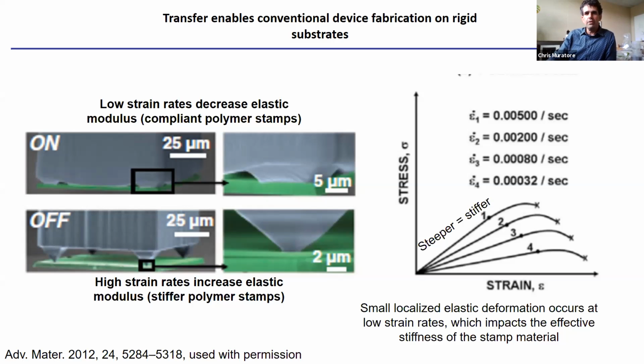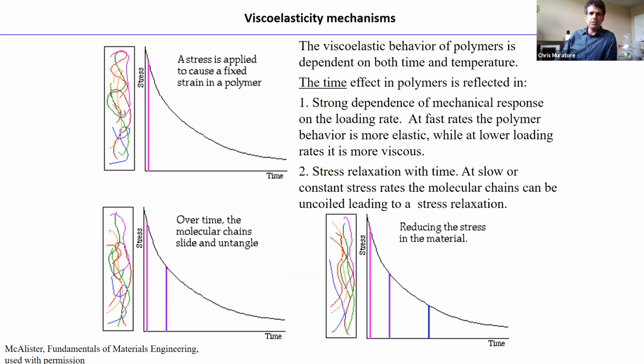the wall. So this idea of controlling the response of the polymer material by controlling the strain rate is useful, because I can strain it quickly in some places and not have transfer because the material is not as compliant, and I can strain it slowly in other places and end up picking up the material off of the surface. So by controlling the strain rate, I control the stamping ability or the pickup ability of these polymer materials.